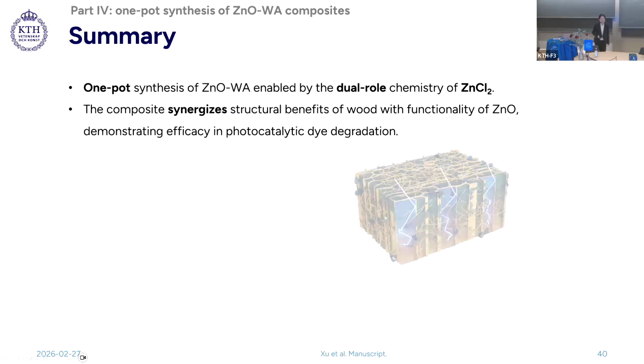In summary, in this work, we developed a one-pot approach to synthesize zinc oxide wood aerogel composites, enabled by the dual function of zinc chloride. The synergistic effect between wood aerogel and zinc oxide enabled applications such as photocatalytic dye degradation.